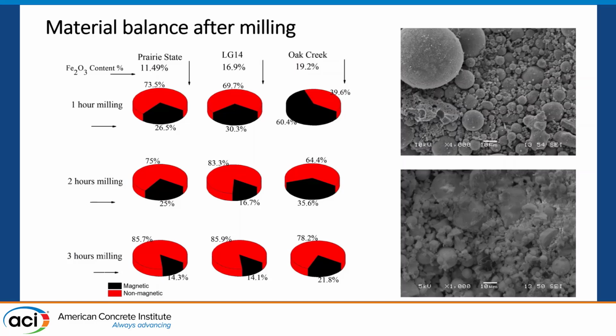And what we demonstrated, you see with milling, this is a distribution for magnetic and non-magnetic. You see you have 19% of material which is iron oxide. And after 3-hour milling, you have 22% of magnetic material harvested. Doesn't mean that this is 100% iron oxide based, because you still have alumosilicates there. I removed the slides on hydration. We demonstrated that magnetic particles work in a very similar way as reference fly ash on hydration. So we don't see that pozzolanic activity is completely destroyed. The idea is we still like to have a magnetic particle which is magnetic on one side and on the other side is still preserving reactivity.